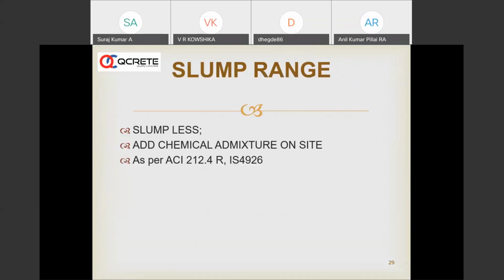Actually, even ASTM C94 is the other method established in America, Canada, etc. They talk about first leaving 10% of the concrete, and the last 10% also you should leave; in between you have to take the concrete. So this is a very important aspect in the retrospective quality control. Then what do you do if we are talking about when the slump is less?